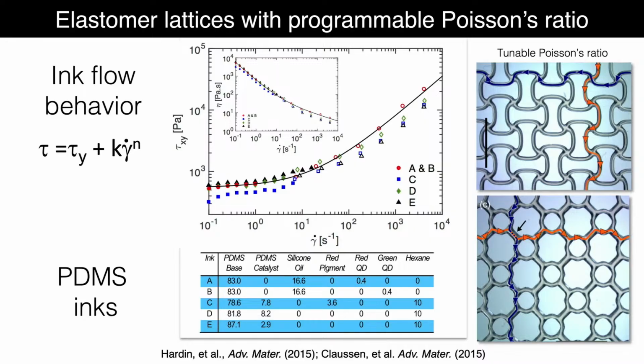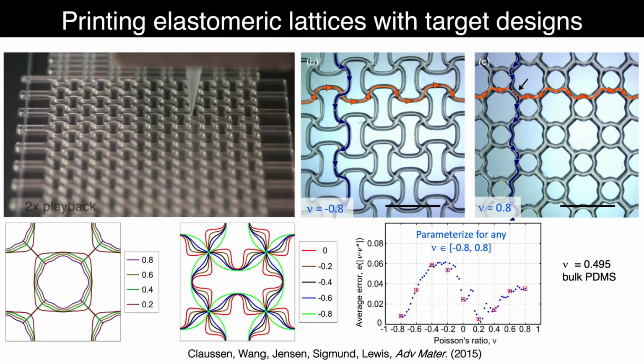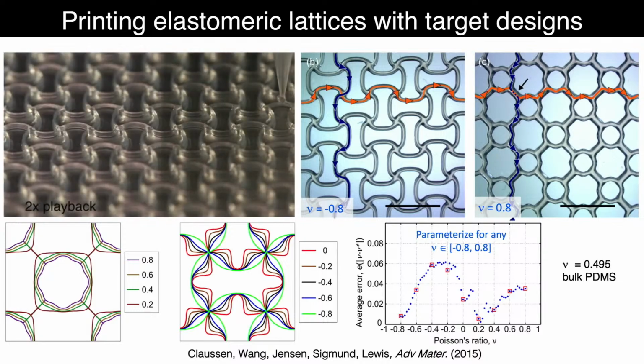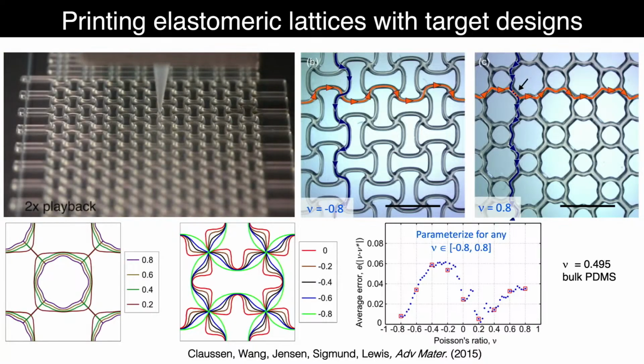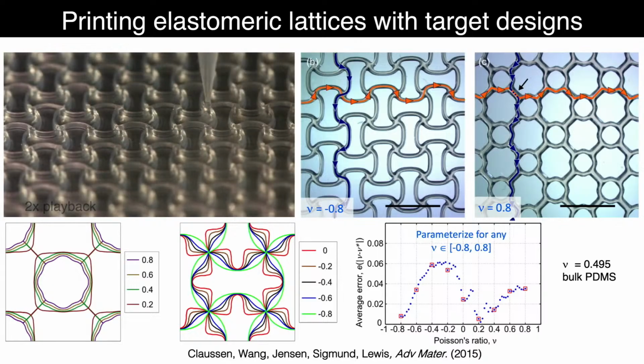These are transparent. And simply by changing the lattice geometry, we could dial in specific Poisson ratio values. Just for reference, the bulk PDMS has a Poisson ratio close to about 0.5. And you can see us printing this architecture here, which has a negative Poisson ratio of -0.8. These are 2D architectures, which is why you could go over this broad range of values. And we, of course, have introduced in these unit cell configurations different modalities. So rather than most materials, which contract in the lateral orthogonal direction as you put them under tension, these can expand, as you can see, when you have a negative Poisson ratio. I'll show you that in detail in the next slide.